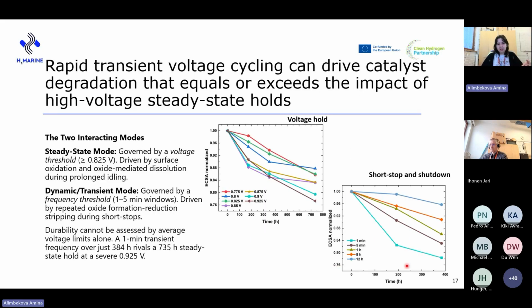When we compare the voltage hold and the short stop and shutdown side by side, we see that both have this threshold behavior. The stressors in those cases are different, because under steady state conditions, under the voltage hold, we observe a limit at around 825 millivolts, above which platinum dissolution occurs quite rapidly due to enhanced surface oxidation.